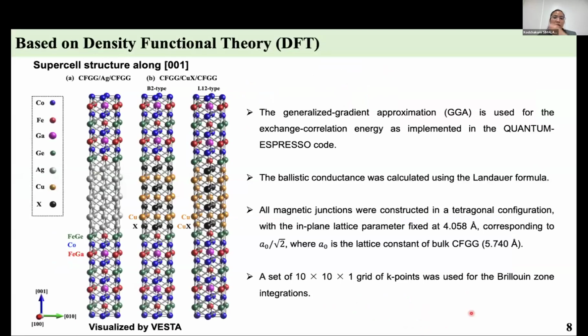Computational method: our calculation is based on density functional theory. The ballistic conductance was calculated using the Landauer formula. All the magnetic junctions were constructed in the tetragonal configuration with the in-plane lattice parameter fixed as that of Co2FeGa0.5Ge0.5 at 4.058 angstrom, as shown here. So the first supercell structure is for the Ag spacer materials, where the interfacial termination depends on the electrode materials. There are three possible interfacial terminations, which are FeGe, Co, and FeGeGa termination.